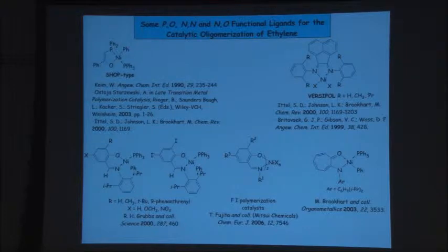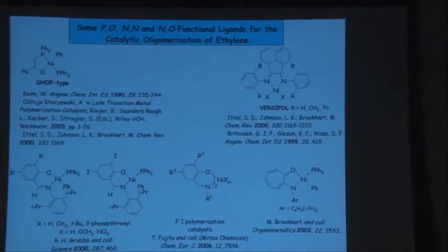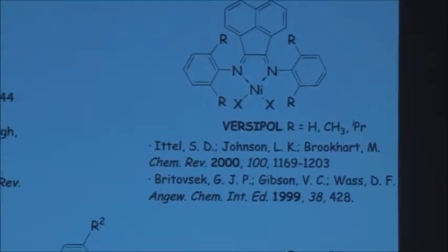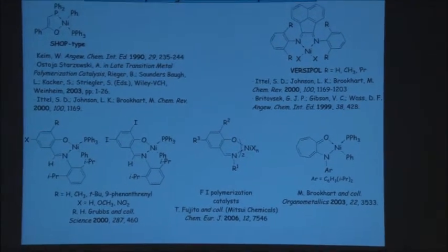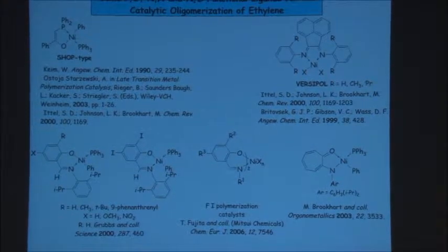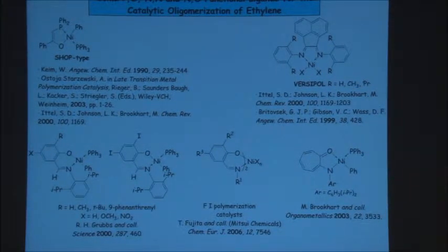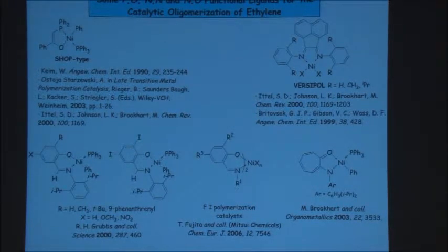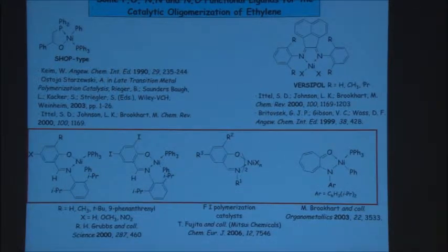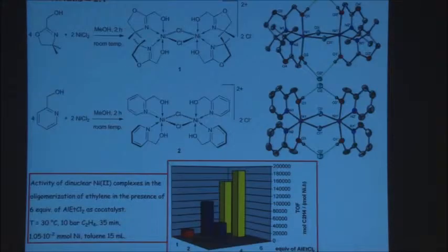Now here you have another example with symmetrical ligands, the chelating diimines that Maurice Brookhart and Gibson have investigated, which was also developed by BP Chemicals. But the others here are NO chelates, so PO chelates, NO chelates, and symmetrical chelates, as I said before: P donor, oxygen donor, N donor, oxygen donor, all based on the system shown here with various groups. So we were interested to look at the systems affording this sort of structures because there are indications from the literature that this NO chelation can be very favorable towards the reaction we want to catalyze.